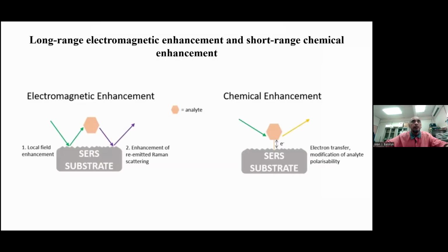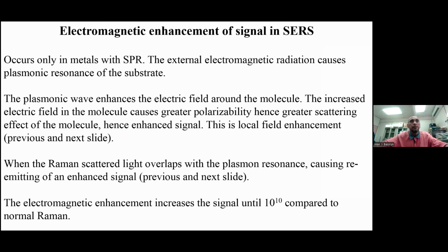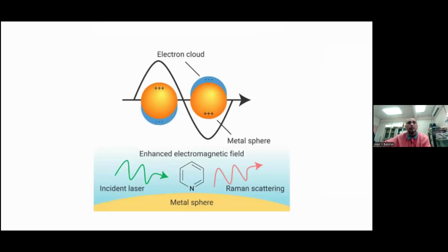For example, look at the left side, the arrow which is dark blue. This is the re-emitted Raman scattering. So you have double effect. So this effect will actually give you the electromagnetic enhancement. This electromagnetic enhancement can enhance the signal up to 10 power 10 compared to a normal Raman or the bulk Raman. So this is a case of the thing.